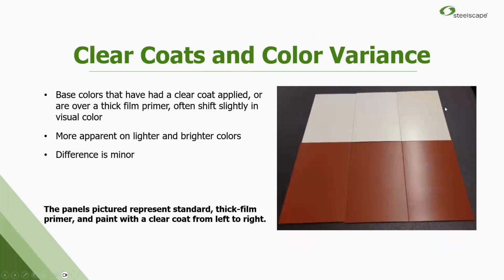So the panels I have here left to right, the white and the red. On the left is just regular primer, regular top coat. And then we have a high build primer underneath, and then with a clear coat. And you can see on the light color that shift. It gets a little darker, a little bit more yellow, but on the red, it doesn't really do much. And this is just an awareness thing that while they're clears, they're not 100% clear. If they were 100% clear and translucent, they wouldn't be able to do their job, and you wouldn't get that extra UV protection out of them.